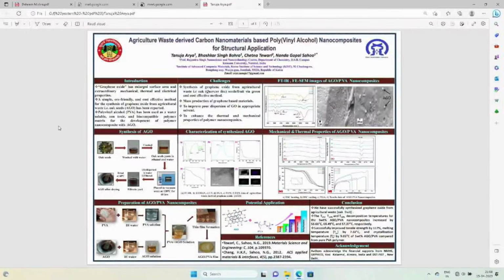From the DSC data, we found that the melting temperature has increased by 7.02 degrees Celsius for 5 wt% AGO PVA nanocomposites as compared to pure PVA. And the crystallization temperature is also increased by 9.06 degrees Celsius for the 5 wt% AGO PVA nanocomposite as compared to pure PVA. Next is the tensile data, which also shows that there is an increase in the decomposition temperature, and tensile strength is also increased by 117%. Next are the applications. We can use these polymer nanocomposite films in packaging materials and also structural applications.